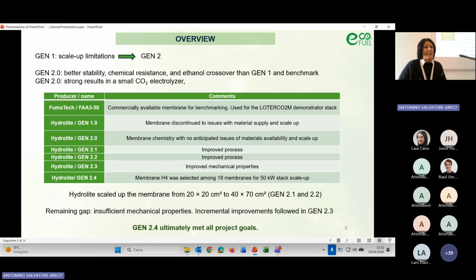So an overview, considering that this presentation is a summary of more than 3 years of activity in the project. We tested a lot of membranes, and we started from membrane generation 1 that has very good properties, but has some issue in the scale up. So we moved to Gen 2 that mainly has the same configuration, but with some improvements. For Gen 2, we had 4 generations. At the end, Gen 2.4, we characterized 18 membranes that have different properties in terms of cross-linking and chemical properties. And one of these membranes was selected for the scale-up and the utilization in the 50 kilowatt stack that at this moment is running.